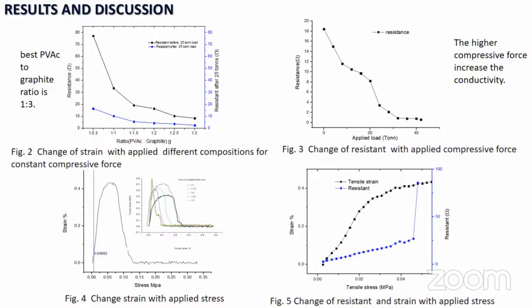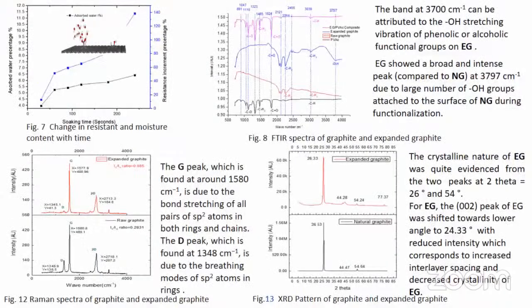We can see the graph in figure 4. The point, we can see the point is 0.04993 strain. This small area is expanded in figure 5 with the change of the resistance and strain with the applied stress. We can clearly see that after a specific point the material will lose the conductivity and become resistive. In figure 7 we can see the resistance change after water moisture absorbance.